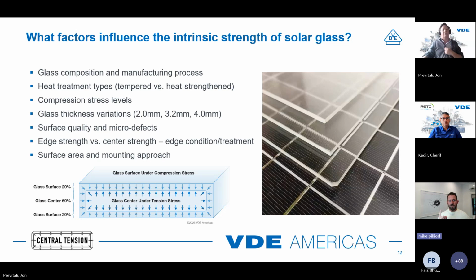Like I mentioned before, surface quality and defects in the glass, these could be edge defects or surface defects, matter because that's where glass breaks from pre-existing flaws. Just for everybody's information, if you clean the window of your car or in your house, you're going to induce small scratches on the surface just by cleaning. You don't need a deep gouge in the glass to cause a rate limiting or strength limiting flaw in the glass. Every surface of glass that's out there has pre-existing flaws on the surface. The goal of glass understanding is that it has a flaw distribution. Every piece of glass has some level of flaw distribution in it across the surface.